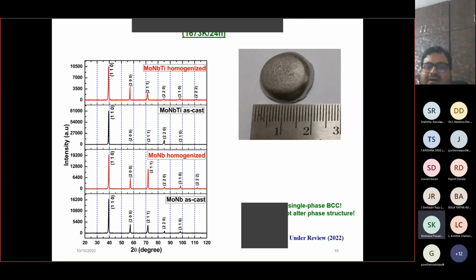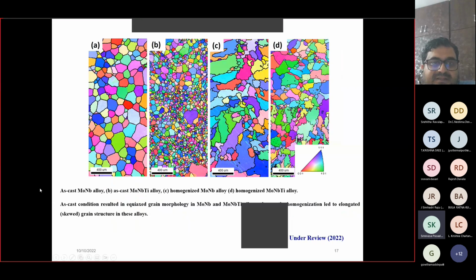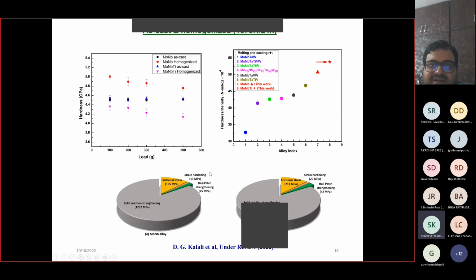And irrespective of that, what we have seen is that the single phase BCC structure that was formed after arc melting has remained stable even after exposing these materials to very high temperatures for longer durations. And titanium, which has a different crystal structure compared to moly and niobium, also did not make any difference. It's the same BCC. And interestingly, this is the microstructure with moly and niobium, and this is the one with titanium. You see that the grain size has decreased. So titanium acted as a grain refiner, resulting in grain refinement. And when we heat treated the samples, you see that the grains have got some kind of skewed morphology, but the average grain size remained intact.